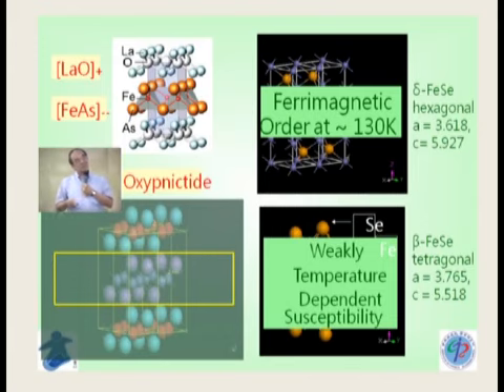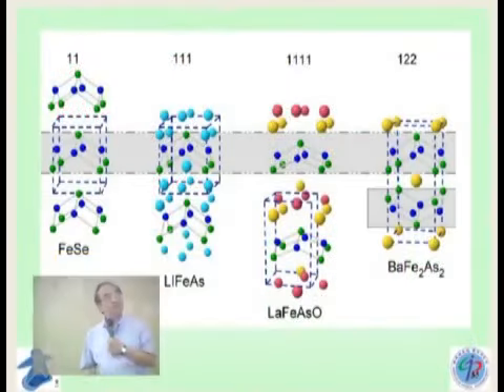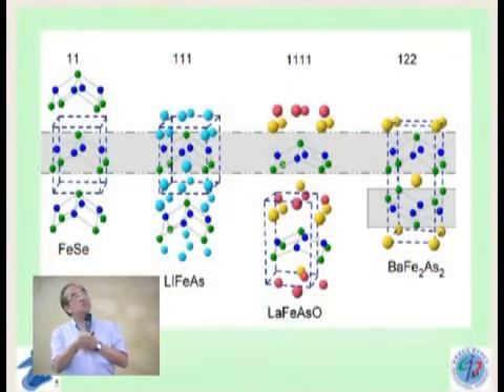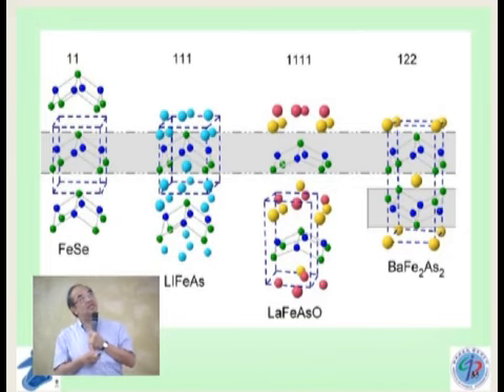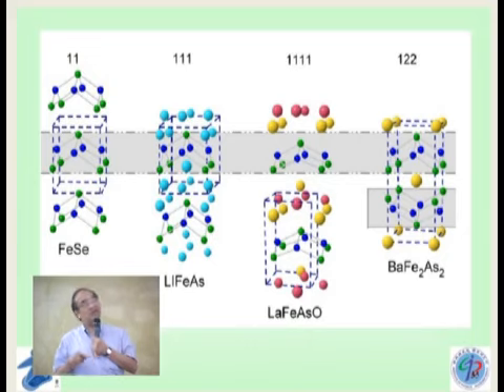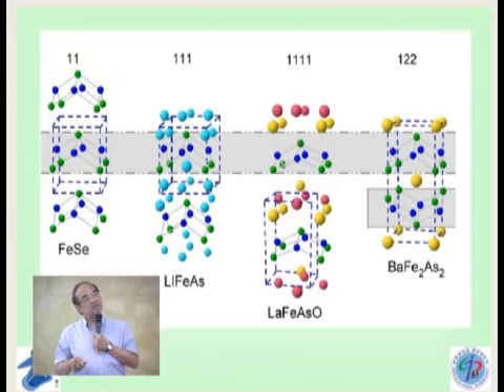We used this idea and started to work on that, and quickly we did find a new compound, we call the 1-1 structure iron selenide, which is superconducting. TC is not that high, only 10 Kelvin. I'll talk about this later. At about the same time, a German group found that you can make a superconductor using the so-called 1-2-2 composition.